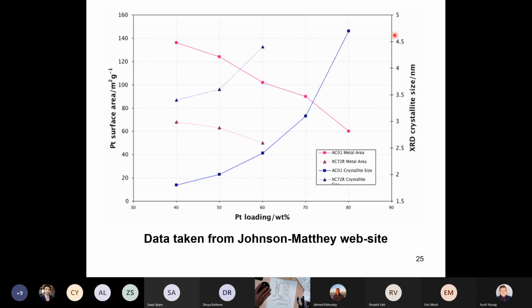So the surface area to volume ratio gets smaller as the loading goes up. So it would be your intent to increase the loading, but not increase the crystallite size, to maintain a high surface area per gram. The way that these catalysts are applied, usually in a solution-based precipitation process, leads to this interaction between loading and crystallite size. And the same is true for the other carbon. As you increase the loading, the surface area drops and the crystallite size goes up.